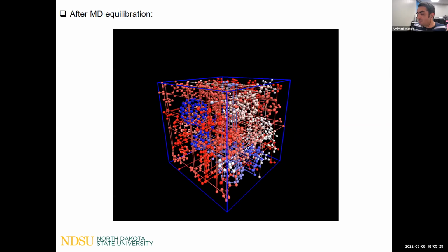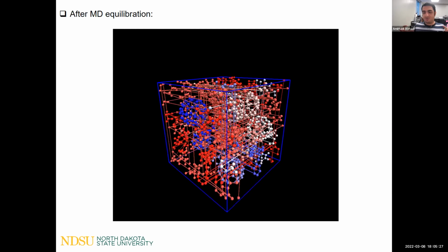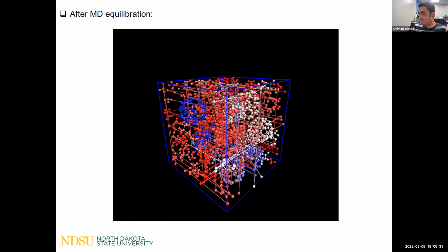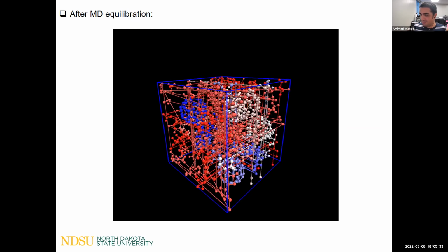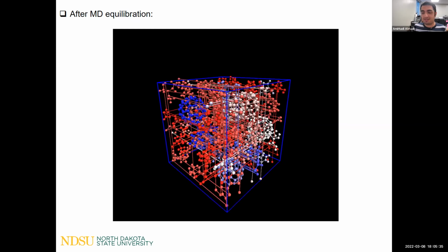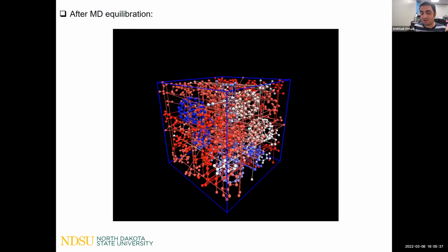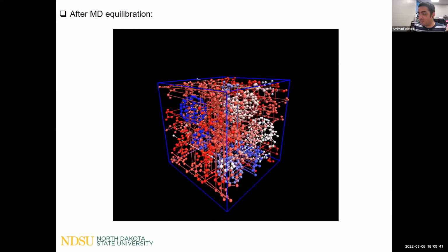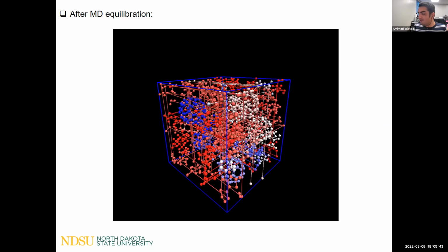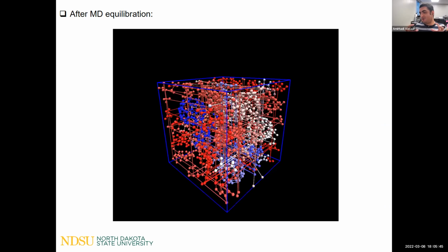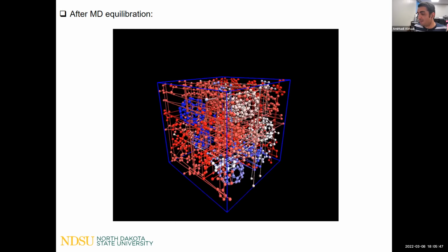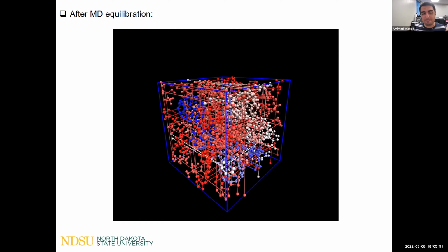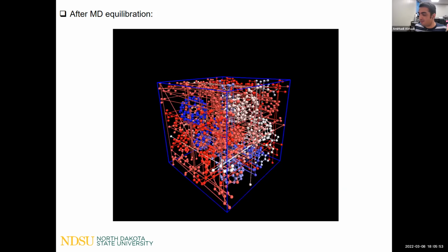And at the end of the simulation at the room temperature and the 1 atmosphere pressure, these are the equilibrated bonds. Yeah, I will use your setting. Dr. Killen, you mentioned using dynamic bond and the VDW setting. I will do that. So here is the 1.3 gram per cubic centimeter equilibrated density, kind of close to the experimental reported values.